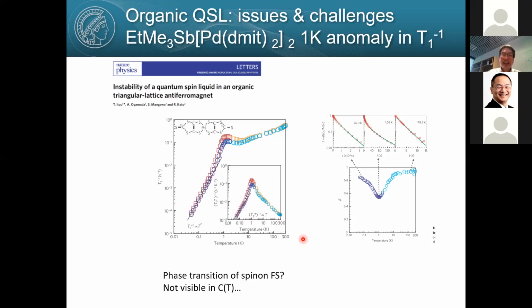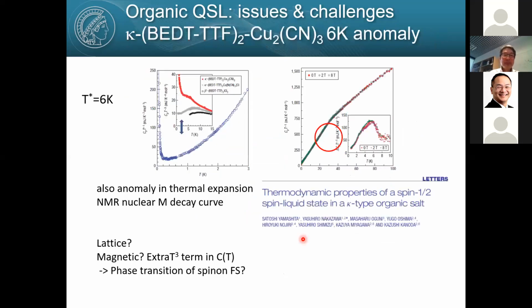So we do see a T-linear term in specific heat and thermal conductivity. Even in this BEDT-TTF compound, you do see some kind of anomaly in specific heat around 6 Kelvin. Okay, this is the T scale, so it's 6 Kelvin. And there's some anomaly in NMR, and we don't know what. So in that sense, we don't understand it 100% yet.